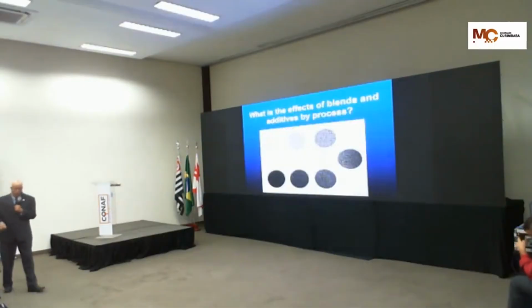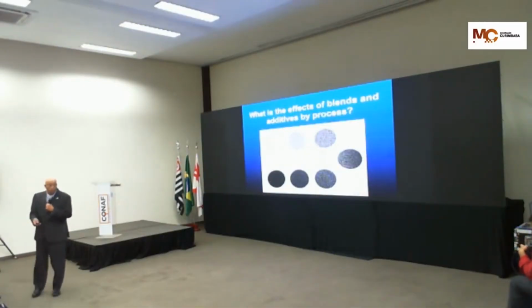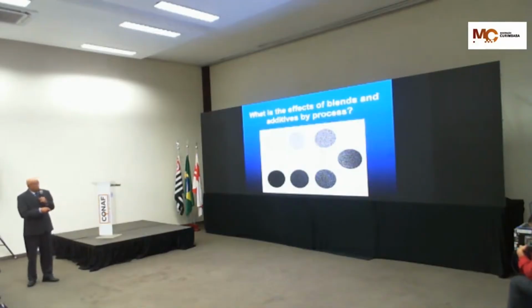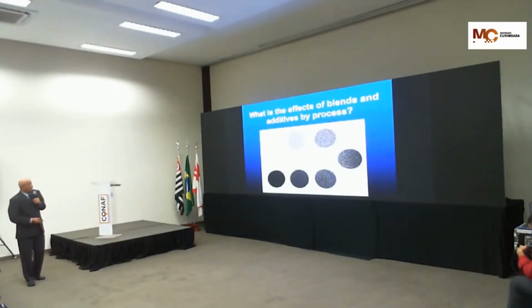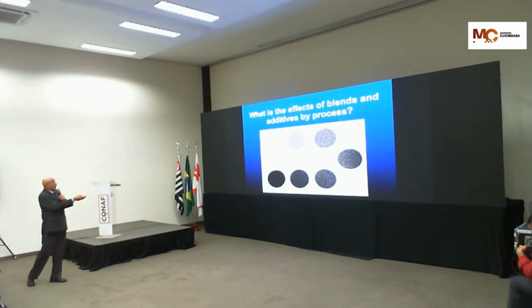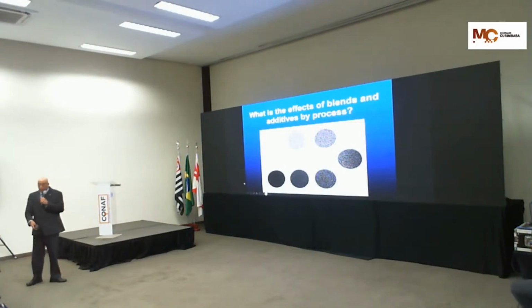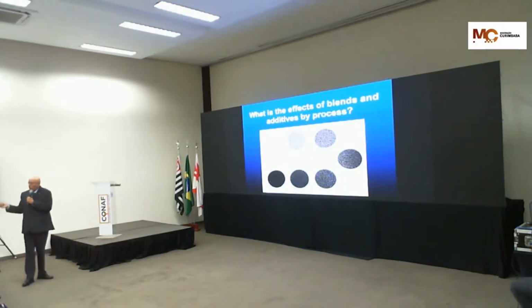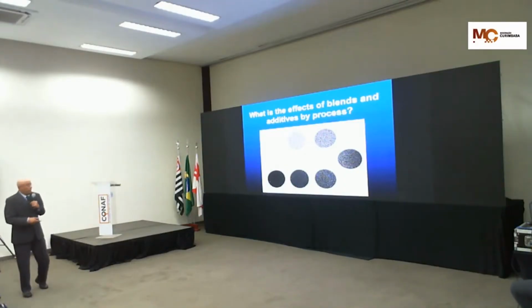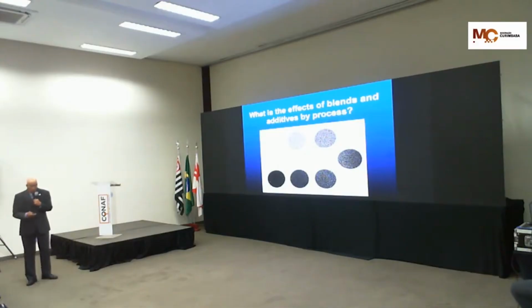But ultimately, whatever the process, hot box, cold box, no bake, we can also try blends in the system. Here is a system with 100% silica sand. Here is maybe 100% chromite. Here is 50-50. Here is 80% silica sand, 20% chromite. Here is 80% chromite, 20% silica, and you can see 40-60, 60-40, any blend you want to try. For heat transfer purposes, what is the benefit, or maybe you want to consider reducing the cost of your aggregate. We can try that.